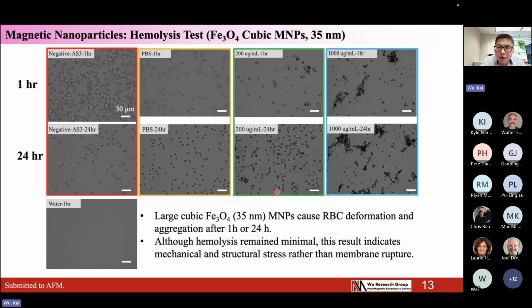As a comparison, we also compare the iron oxide cubic particle with 35 nanometer, very large cubic particles. You can see that this particle first will introduce nanoparticle aggregation, very severe, the RBC and the blood cell aggregation. In addition, it will also disrupt the membrane of the cells. You can see some spikes on the surface of the red blood cells, which tells you that these large cubic Fe3O4 nanoparticles are not well compatible with the human blood. So this tells us that this particle cannot be used for in vivo applications, such as injection into the human blood veins.